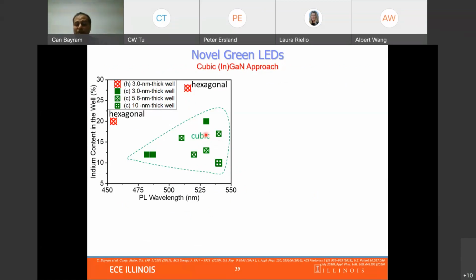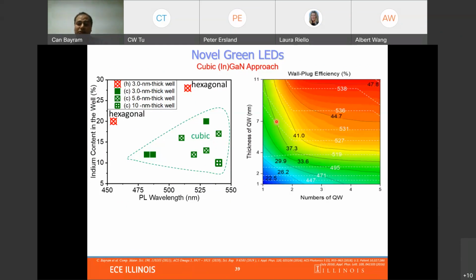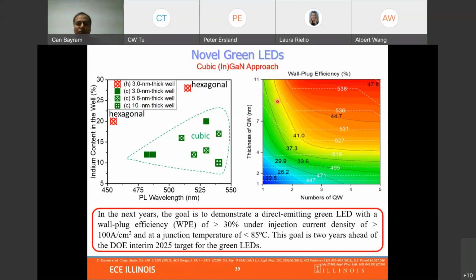So basically, by just using cubic nitrides, we can reduce the indium content and indium thermal diffusion and other things, of course. And our own designs also show that by going to a thicker quantum well, because of the nonpolar nature of the structures, we can reduce the number of quantum wells and enable very highly efficient green LEDs.